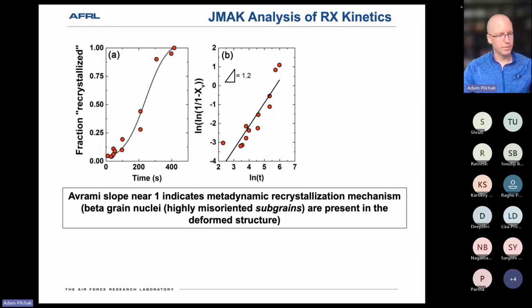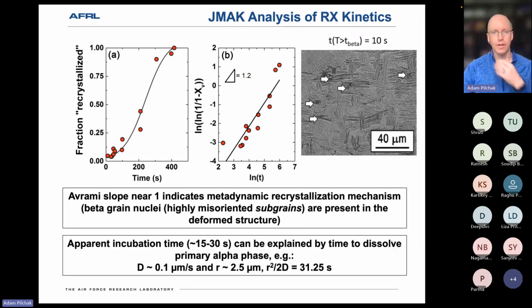The other recrystallization mechanisms, more classical discontinuous recrystallization and grain growth, may have an Avrami slope closer to 3 or 4, if I'm recalling right. But this was important here in that it's telling us that the recrystallization nuclei are already hidden somewhere within our sea of red, nominally single crystal orientations, and so we just need to find them. We did find a small incubation period, and so this analysis is actually scaled for that time a little bit.